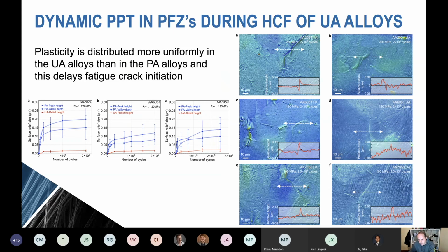And we have this bigger localization of plasticity, 100 to 200 nanometers in size after the sorts of numbers of cycles here. And this is the equivalent case for the underaged material. Same number of cycles, and we typically now have the magnitudes of the plasticity localization is 50 nanometers or less. So there's a huge change in the distribution of plasticity. It's much more uniform in the underage state. And part of the reason is that we're able to remove that contrast between the grain interiors and the precipitate-free zones by dynamic precipitation. So it's sort of like a form of self-healing.